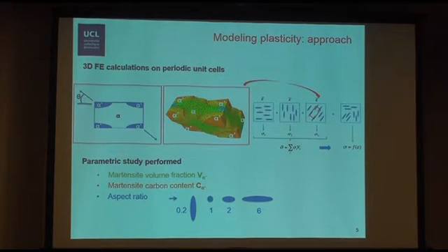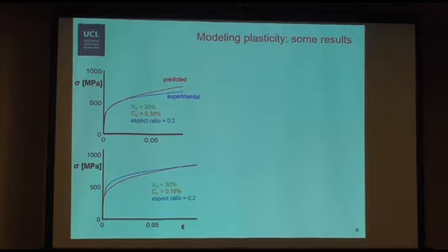And those parameters are martensite volume fraction, martensite carbon content, and morphology that we changed through the aspect ratio. We took oblate ellipsoids for the case of platelets. We took spheres compared to the equiaxed case, and two values of prolate ellipsoids. Here are results of this parametric study.